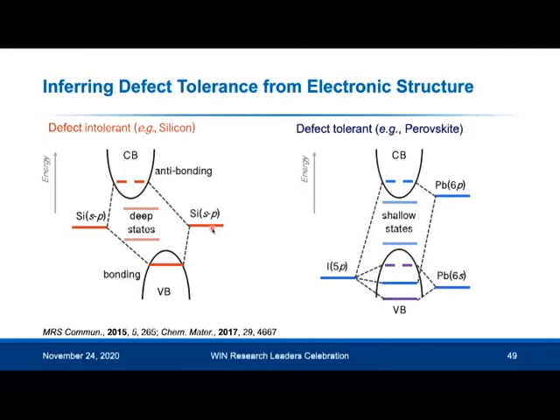And this is very harmful, causes high rates of non-radiative recombination. By contrast, the perovskites have a very different electronic structure, which results in the atomic orbitals being close to the bands rather than in the middle of the band gap. So when you form defect states, the defect states will form resonant within the bands, or if they do form within the band gap, they'll be shallow within the band gap, meaning they're close to one of the band edges, which is much less harmful, gives much lower rates of non-radiative recombination.